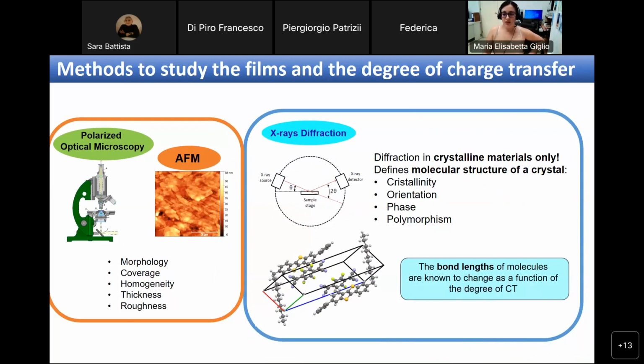So basically, going deeper into the methodologies, we use polarized optical microscopy and atomic force microscopy in order to study the morphology, the coverage, the homogeneity of the films, as well as the thickness and the roughness. Then we perform X-ray diffraction that works, of course, only with crystalline films, in order to define the molecular structure of the crystals, the orientation, the phase, as well as the polymorphism, which is all the ways that the crystals can form.